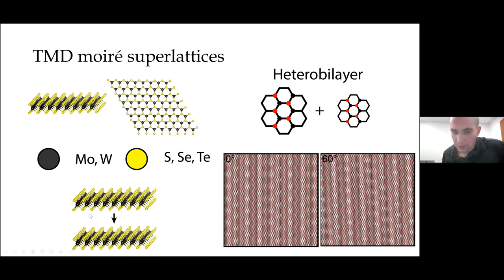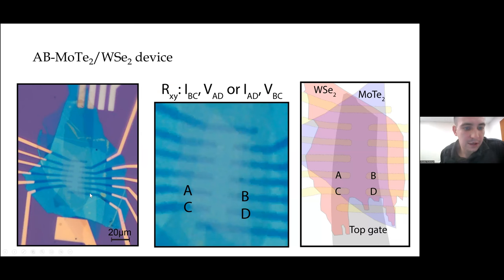So on the left, I'm showing you an optical image of the device that we'll be talking about. It looks a little strange for reasons that are easy to understand. The system that I'm talking about is a tungsten selenide and molybdenum telluride heterobilayer. The molybdenum telluride is air sensitive, which means these devices are fabricated in a glove box and encapsulated in boron nitride. The way that contact is made to them is contacts are deposited first onto a piece of BN, and then the device is placed on top, and then another piece of BN is placed on top. So the idea then is that the contacts themselves are encapsulated in boron nitride, and that's sort of why they look dark relative to the background.